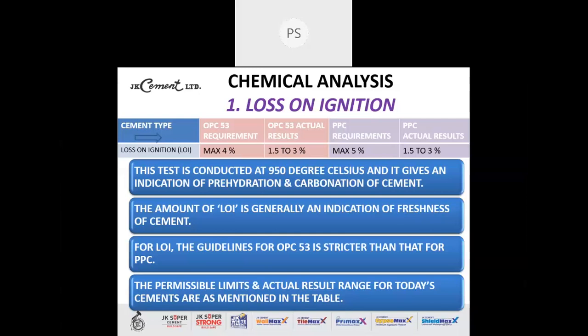For LOI, the guidelines for OPC 53 is slightly stricter than that for PPC. If you see above, it is 4% for OPC and 5% for PPC. This is because PPC has an additional content of fly ash that is added to it during the manufacture, and this fly ash may contain some carbon content, unburned coal content, and due to which the LOI may increase. So that is why the limit is 5% for PPC. The permissible limits and actual result range for today's cements are as mentioned in the table above. Next please.